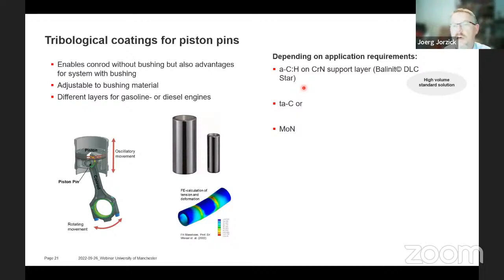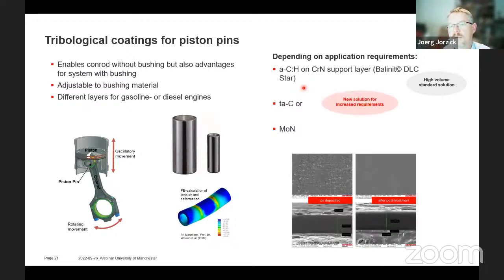However, for some other or higher requirements, we also have this ta-C, which is a new coating. Here you see again, because we use the arc evaporation process for this, as deposited, you see a quite rough surface, and after some post-treatment, this surface is much smoother. So that is the new requirement, and due to the higher loads in the systems and less lubrication or lower viscosity oils, this is something which is now coming up and which the customers are requiring.